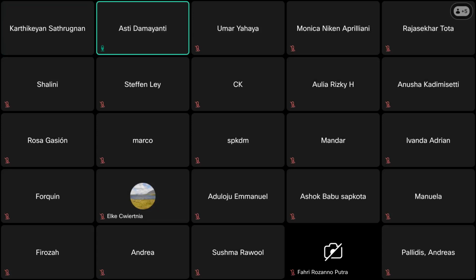Okay, great. And can we perform double shot analysis using the RxPy method? Actually, if your purpose is generally for polymers and additives, most of the applications that we have shared here are run at 300 to 400 degrees. So if your intention is to look at the additives and polymer, most likely you will have that information in one single run at a temperature like 400. So we do not see any application where we run the double shot with reactive pyrolysis. Yeah. Okay, great. Thank you, Dr. Karthik.